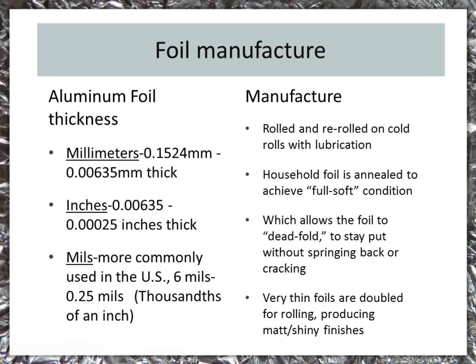Foil is generally defined by U.S. manufacturers as having a thickness of between 6 mils and 0.25 mils, or thousandths of an inch. Kitchen foil today is usually less than 1 mil thick. The rolled foil intended for industrial applications is work-hardened, but the household product is heated to anneal it prior to final inspection. This produces foil in the full soft condition, able to dead fold, and that means stay where it's put without springing back or cracking. This annealing also burns off any oil lubricants used in the rolling process.